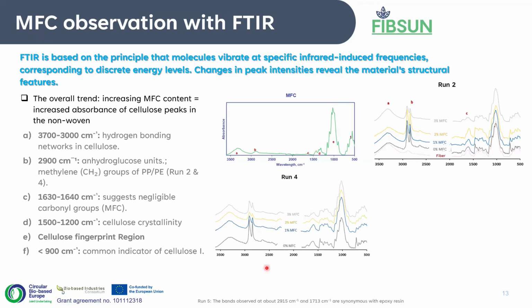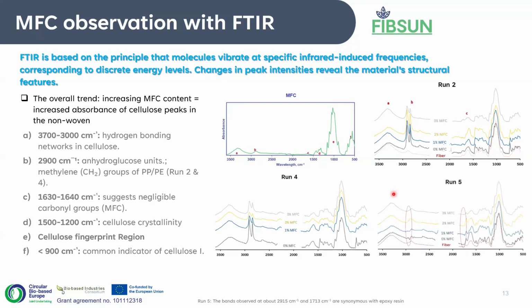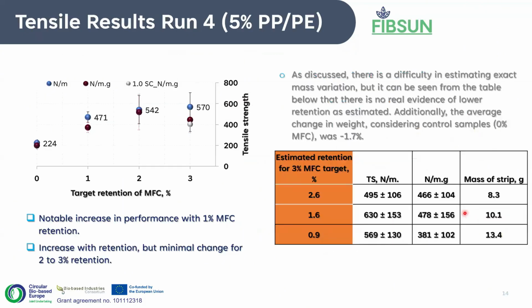While not directly visible from these two, what we also notice is that when we line together the round 2 and round 4 non-wovens, there was already a difference in terms of the intensity of the peaks that are aligned with the PPPE binder, which is typically due to the lower incorporation rate. And in the case of round 5, which has a slightly different binder, we don't see this typical PPPE peak, but we see that here in this region for epoxy.